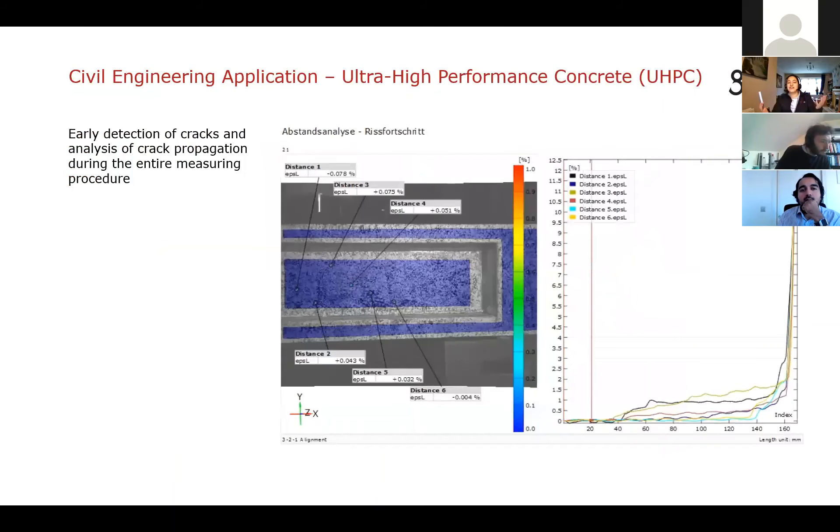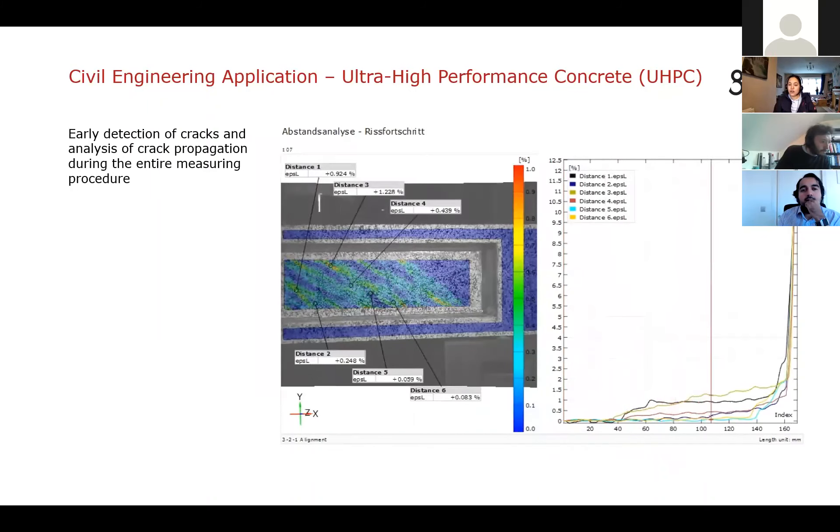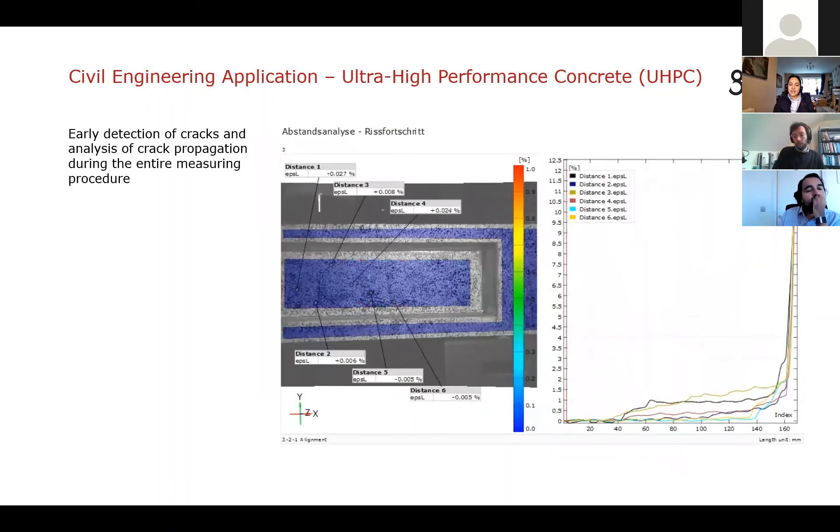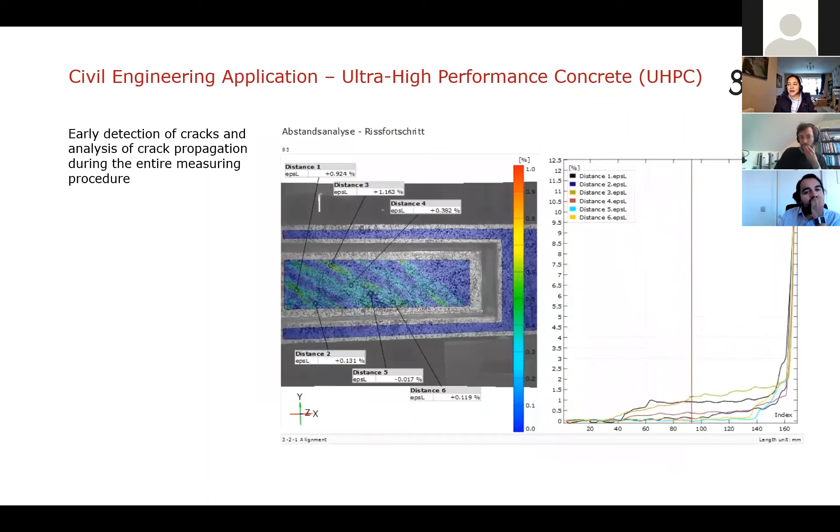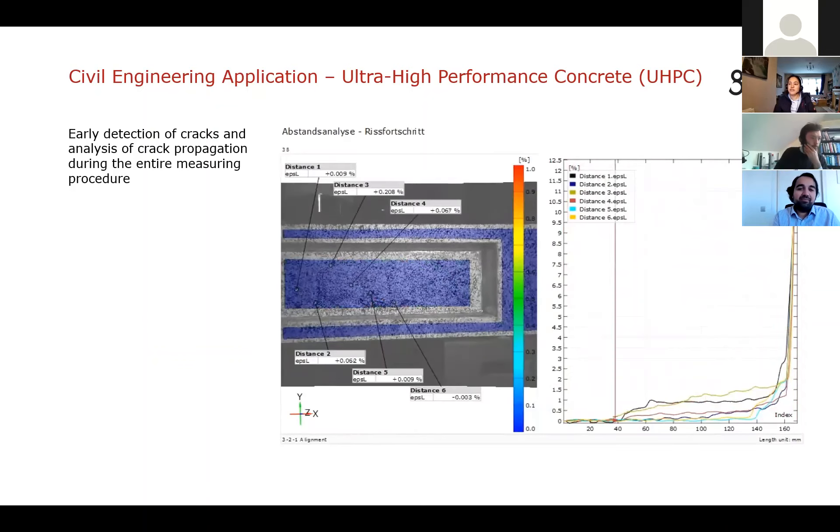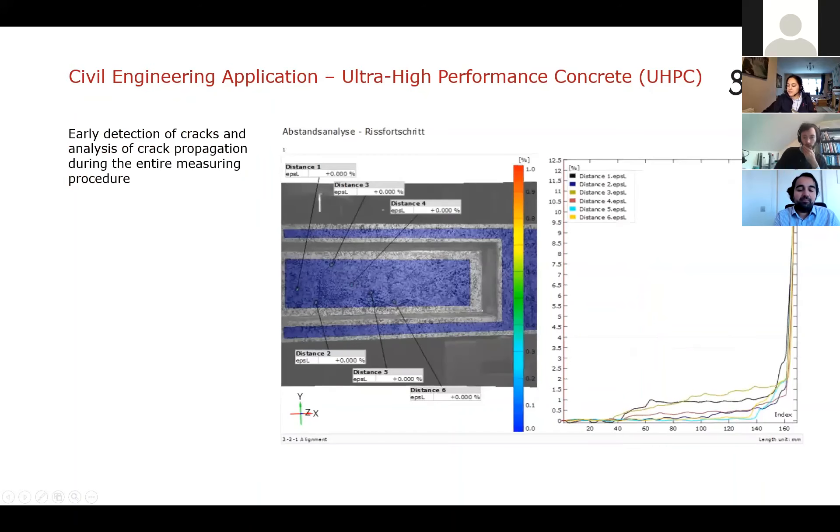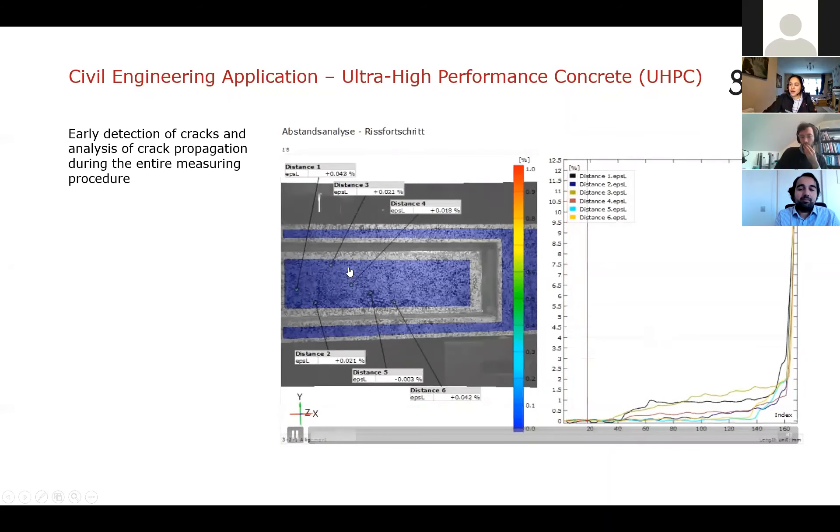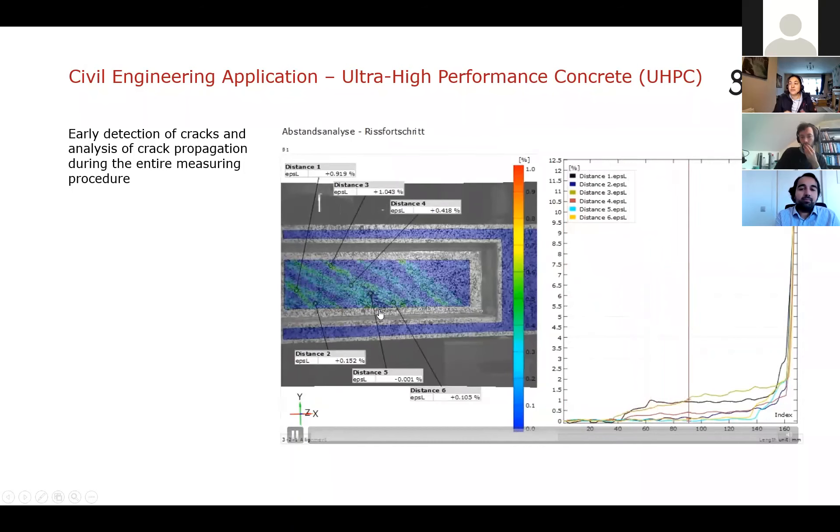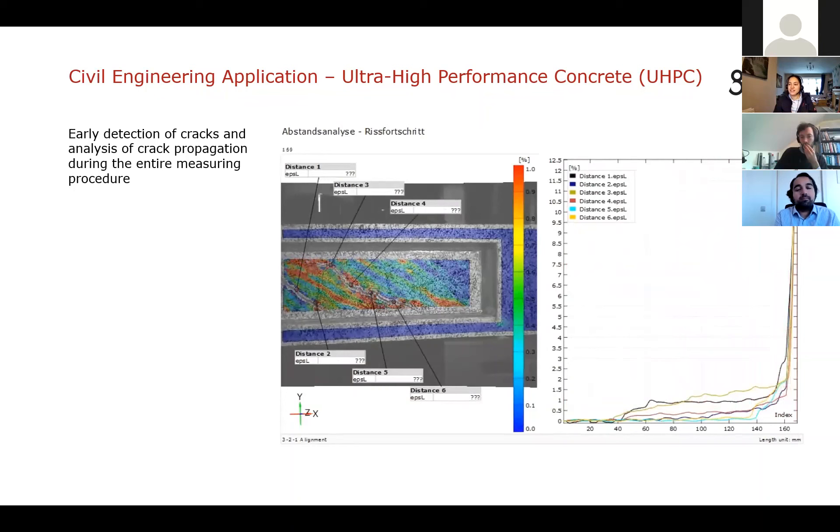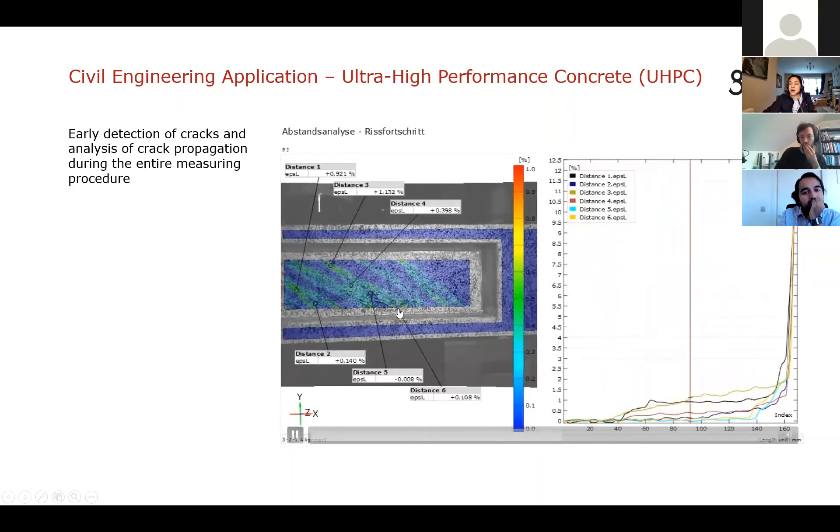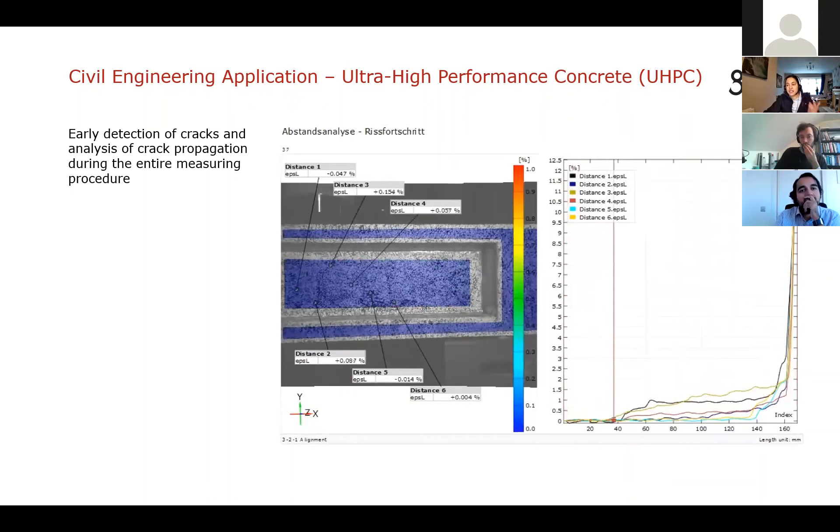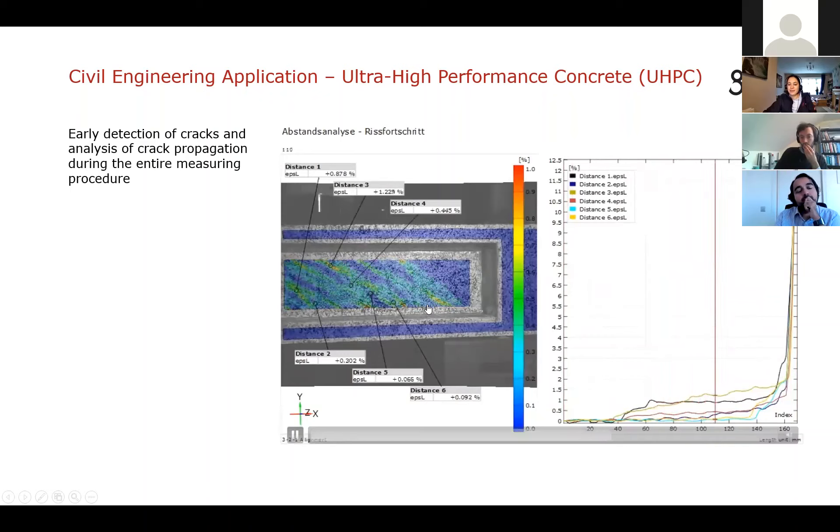Going to sort of the opposite end of the scale here, we're looking at a civil engineering application. So here we've got a concrete support that's under sort of a three point bending test. And one of the things with concrete is you can't really predict how or where it's going to crack. So ideally, you need a full field measurement process to measure it because you wouldn't know where to apply your strain gauges or your sensors. Sorry, I've got a new mouse and it's super keen to move to the next slide. So this is a good example of where the full field data is really going to help us out here. So if I just play the video again, the parts that sort of turn red, so experience the higher levels of strain. This is sort of almost predicting where the part is going to crack and then we can see what it does crack. It does crack along this line here. So almost the first part in the sample to experience any amount of strain. But of course, because concrete is an inhomogeneous material, it's very hard to predict where this is going to happen in such a test.